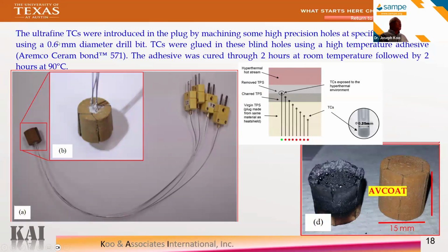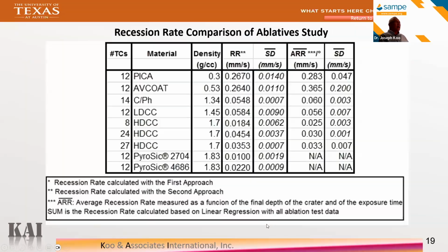And you can see we use ultrafine thermocouples. These are roughly 0.25 millimeter, or 250 micron. We are able to insert these sensors into the material at different stack distances from the front, and we were able to collect the data, which is what you're seeing. It's one of the materials that we received from NASA, the AVCOAT material, and this technology can be applied to examine different types of material.